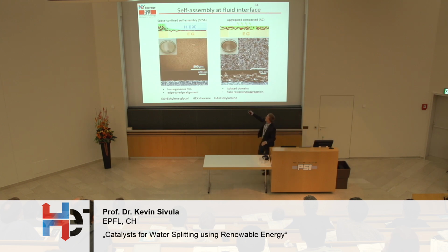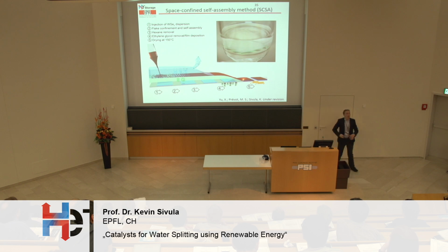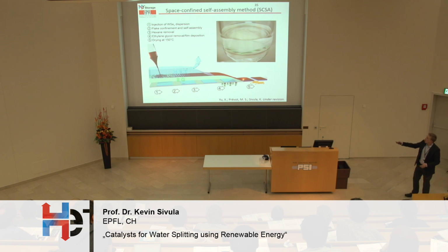In fact, if we look at the SEM here, we see we have almost a monolayer of these flakes on top of our conducting substrate and a relatively homogeneous film formation compared to this case, where we have big aggregates when we use this traditional approach. Now, finally, we leveraged this approach to develop a way to put this onto electrodes, and here I'm going to show you another video. We think that this can be actually used in a roll-to-roll type of a system, but